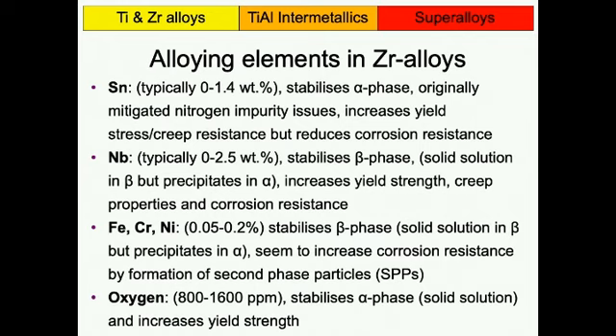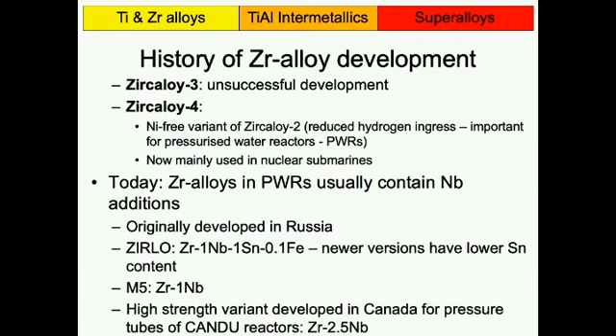So just a list here of the alloying elements and what they might or might not do. I should point out that to a large extent we don't always understand the exact role of these elements. They work, but why they work is often less clear than you might think. Tin. So I've already mentioned tin. In zirconium, it is considered to be an alpha stabilizer, and in principle, it should also be the case for titanium. It mitigates nitrogen impurity issues. Although that has become less of an issue, because simply the zirconium that is manufactured today has much lower nitrogen content.